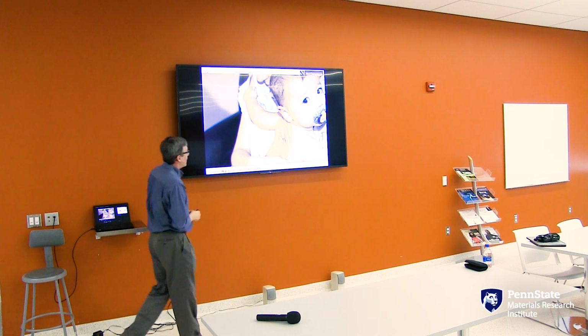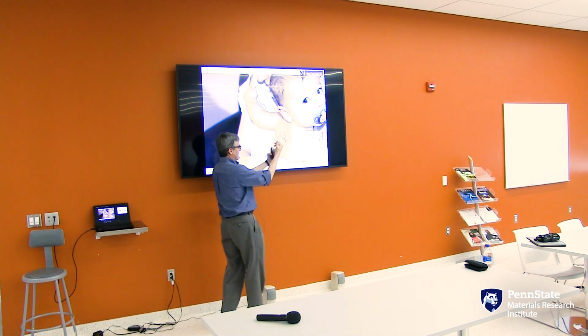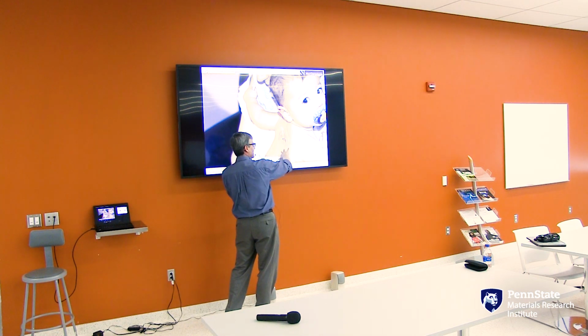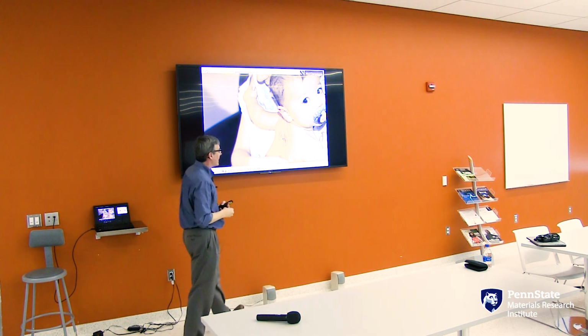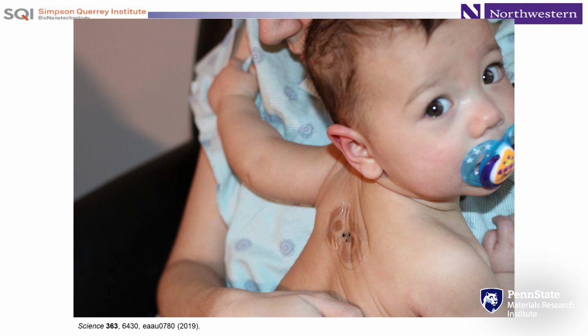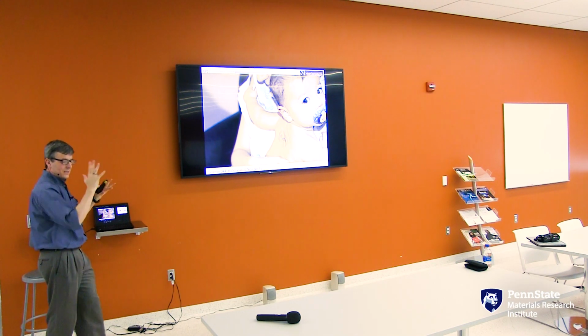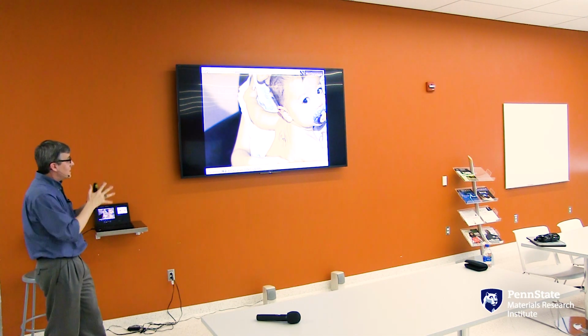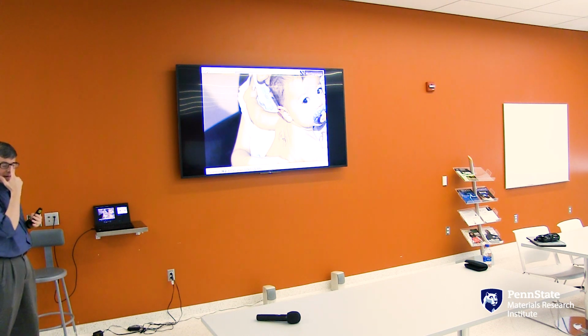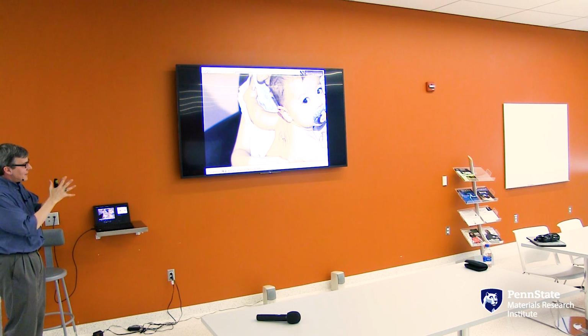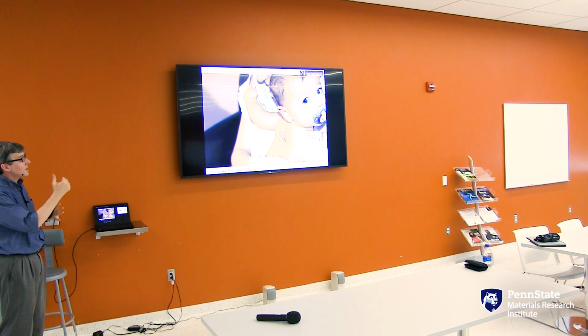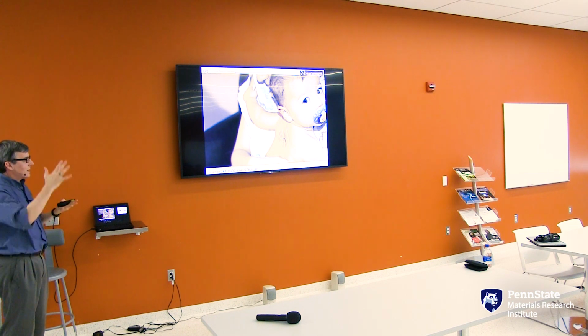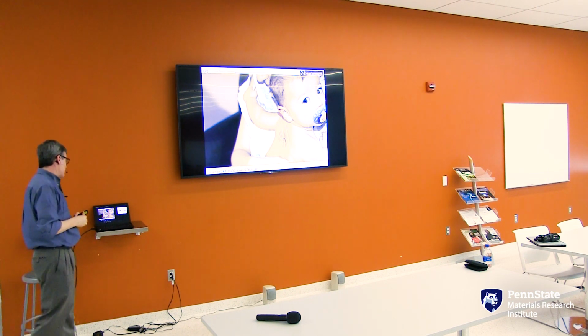place to measure ECG. But here you can see that the skin is wrinkling in a natural way as the baby rotates around. And the device, because it has this skin-like characteristic, can just follow that wrinkling without any kind of mechanical constraint. And so that reduces or eliminates any kind of skin surface irritation or discomfort associated with the device. It also turns out to decrease the propensity for delamination. Because the device is so thin and so soft, the interface stresses are greatly minimized by that kind of construction. So the degree of adhesive that's needed to keep these devices on the skin is more than a factor of 10 lower than the adhesive strength of the tapes that are needed to keep the wired devices adhered.